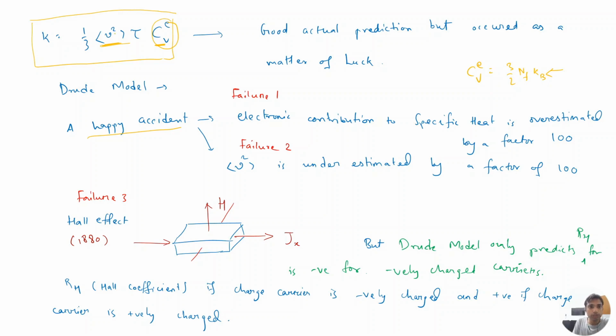And the average velocity is 100 times more than the value. So in the Drude-Lorentz model, this V square is underestimated by a factor of 100. But since both are multiplied, and one is underestimated by 100 and the other is overestimated by 100, the two wrong factors cancel out, and what we get is the actual value. So it is a kind of happy accident. But when we look closely, the specific heat is overestimated and the average square velocity is underestimated.